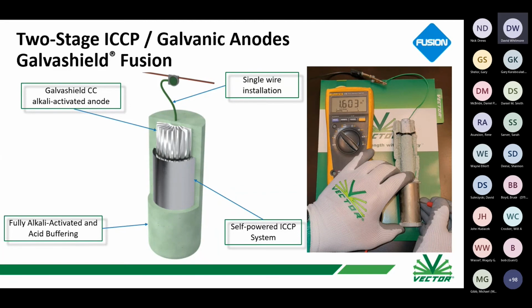You can see a cutaway. Inside this anode, there's actually a battery powered impressed current anode, which is this lower section. And then there's a galvanic anode that's part of it. So when you connect this to the steel and you pour the concrete around, or in this case, you're embedding it in a hole in the concrete, then the impressed current is going to work first. It's going to push more current to the steel because there's a higher driving voltage there. And then when this essentially battery expires, then you're going to be left with the galvanic anode that is continuing to pass a lower level of current.